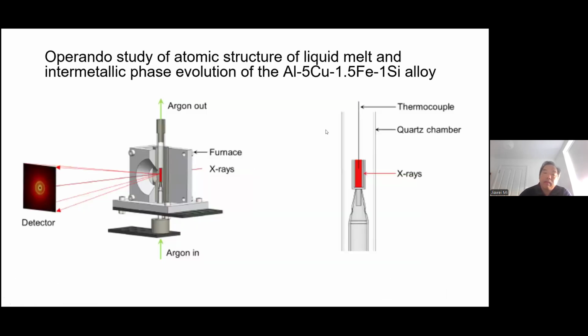And again, I adapted this furnace I have, which has an X-ray shining onto the sample. The furnace has a window open, which allows the diffracted beam to be recorded onto the detector without anything blocking it. And this is the sample. So you have the sample here. We put the thermocouple directly measuring the temperature, immediately above the X-ray point, so you know exactly at this location how the structure changes versus temperature.